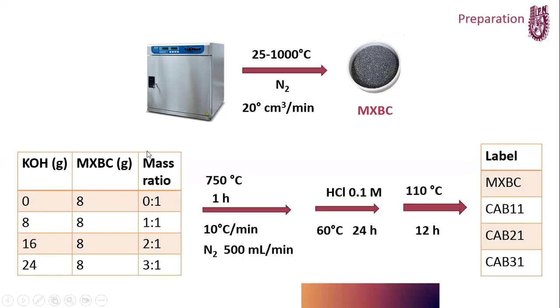Potassium hydroxide and bituminous carbon were mixed at mass ratios of 1:1, 2:1, and 3:1. Activation was carried out with these conditions. Then the activated carbons were neutralized with a solution of hydrochloric acid during 24 hours. And finally, samples were dried in an oven at 110 degrees for 12 hours. The label of the samples contains the mass ratio used for the preparation.